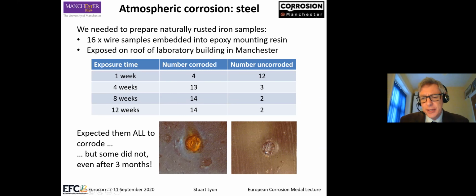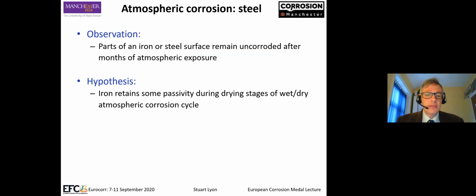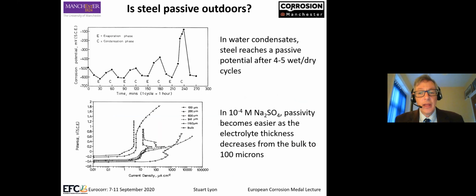Why would that happen? This implies that there is something controlling or stopping that corrosion from occurring, probably because the material is passive. So based on this observation, one of the hypotheses I ran with first is that iron or steel retains some kind of passivity during the corrosion process in the atmosphere of wetting and drying. So if we have evaporation-condensation cycles, we can see after a very short period of time, 4 to 5 wet-dry cycles, the steel reaches a passive state.